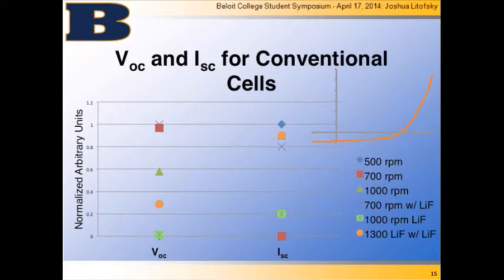Again, I mentioned this is really volatile. When we start testing them, we have no idea how well these cells are going to do. So when I got this data, it was as much a surprise to me as to everybody else in the lab. This is pretty much supported by the literature. They don't have an optimal charge generation layer, so 100 nanometers hasn't really been set as the optimum, although for the production that we were doing, we found that 100 nanometers was the optimal thickness.